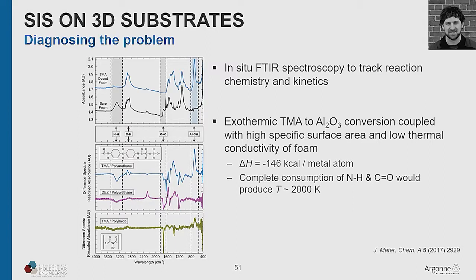One is you can expose it to less trimethyl aluminum, so all you need is enough to functionalize the surface, so you can control your dose. Another thing you can do is to go to something like zinc oxide, a different oxide precursor. It's a less exothermic reaction, and so less heat is released. It gives you more flexibility. Or you can just replace the polyurethane with a different polymer, like polyimide, which is just more thermally stable, for example, and has also a different number.